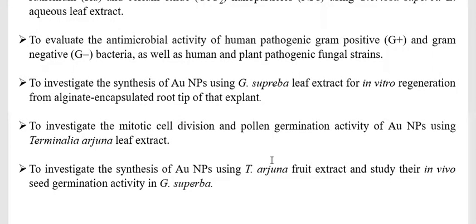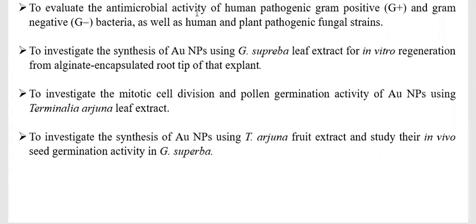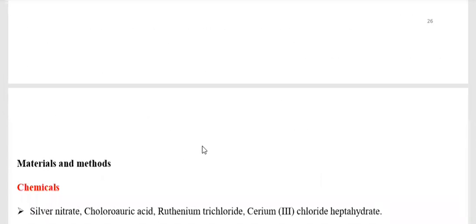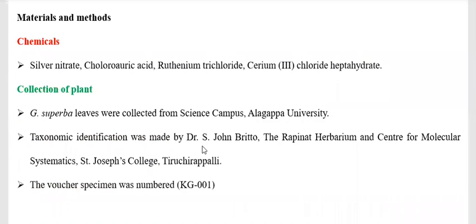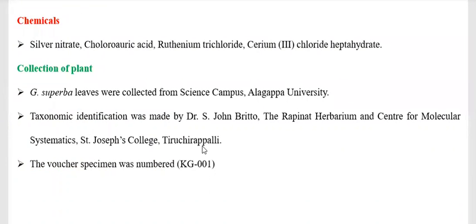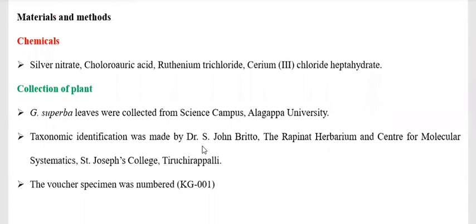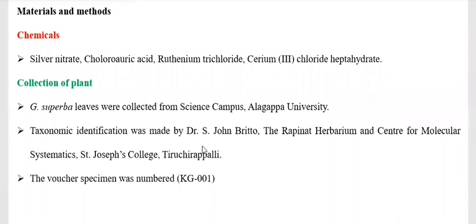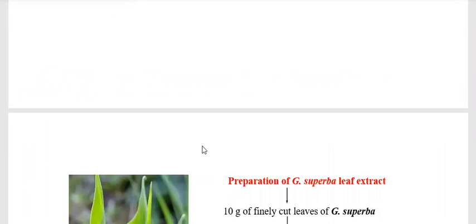We are using a simple, already well-known method: 10 grams of fresh cut leaf and 100 ml of double distilled water, boiled at 50 to 60 degrees for 5 minutes. Filter through Whatman filter paper. The 250 ml filtrate is stored at room temperature. Further, 1 millimolar of each salt is used with 5 ml of plant extract. You get the final product. For metal oxide, you get the final precipitate, calcined at 400 degrees for 2 hours. You get the cerium oxide nanoparticles. It was characterized by UV, fluorescence, XRD, and AFM analysis. UV analysis shows the surface plasmon resonance peak.